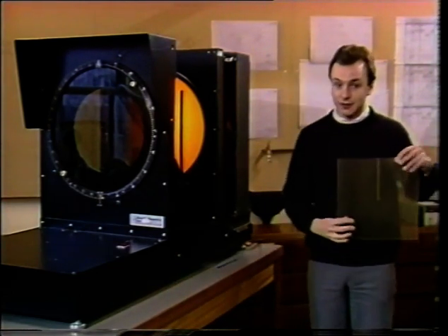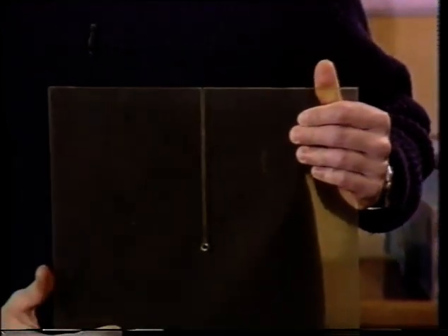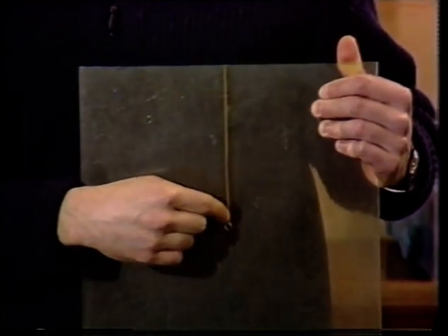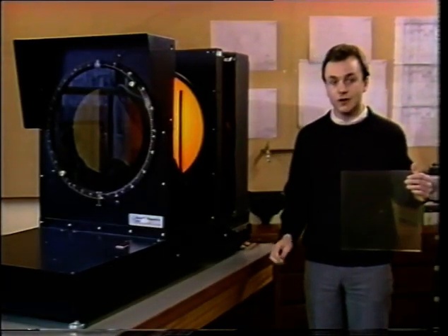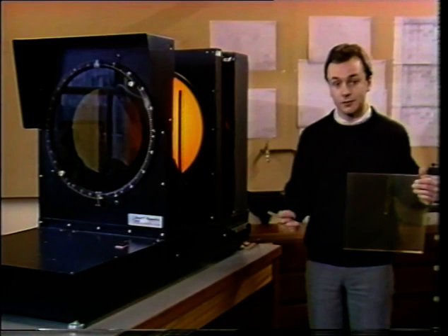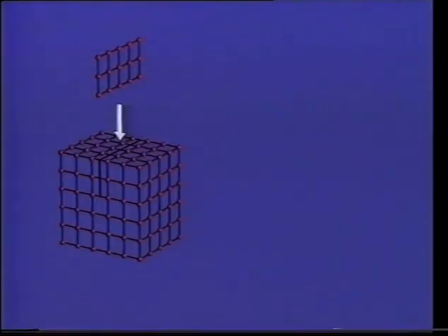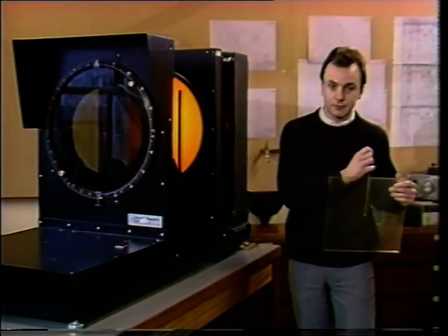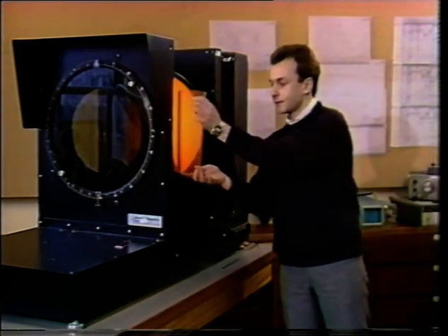You may be surprised to see that this is our model of a dislocation. It consists of a sheet of epoxy resin into which we've drilled a central hole. From that hole, we've machined a narrow slit to the edge of the sheet. We're going to represent inserting an extra half plane of atoms by inserting this shim into the photoelastic sheet. The model is now dislocated. I'll just remove that shim and we'll insert the undislocated model between the two polarizing filters.